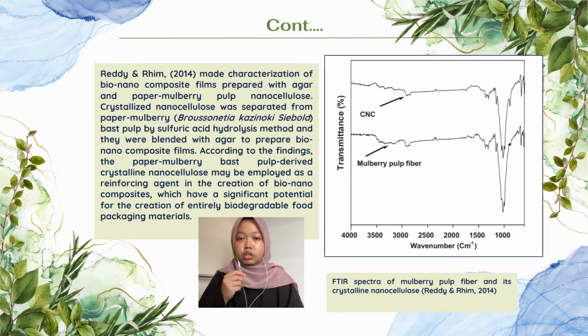Crystallized nanocellulose was separated from paper-mulberry bast pulp by sulfuric acid hydrolysis method, and they were blended with agar to prepare bio-nanocomposite films. The results of FTIR show that there was no distinctive change in absorption peak positions of the CNC compared with those of the mulberry fiber, which indicates that the acid hydrolysis of mulberry fiber did not affect the chemical structure of cellulose fragments.